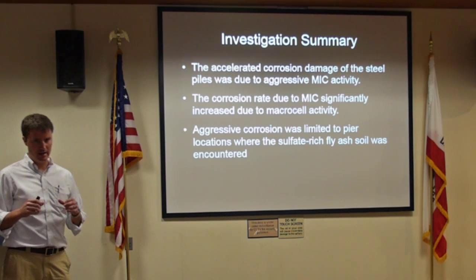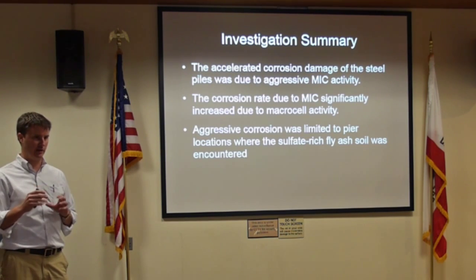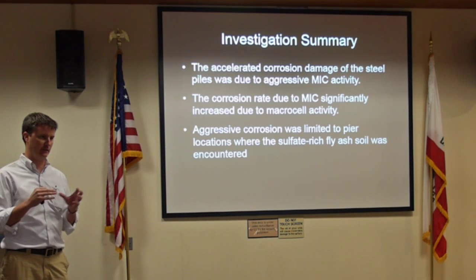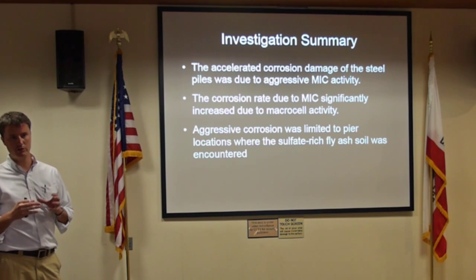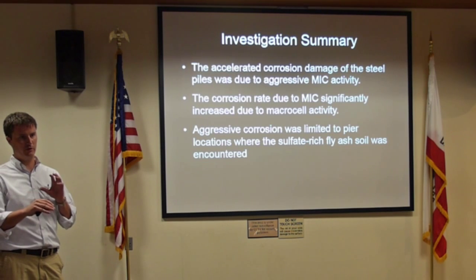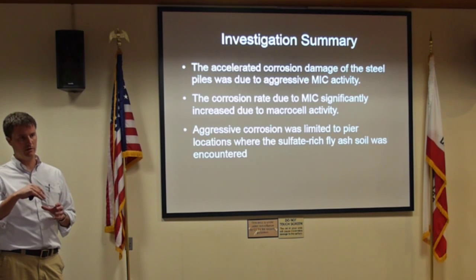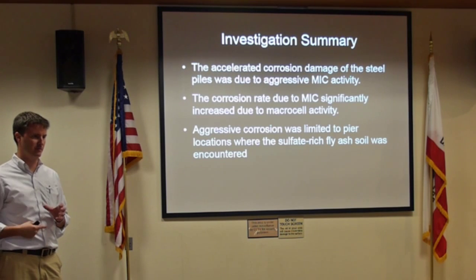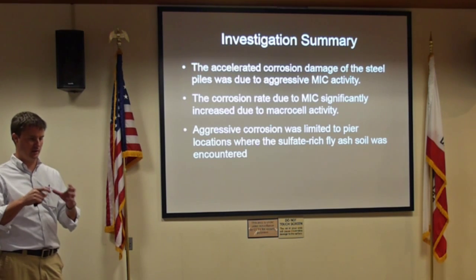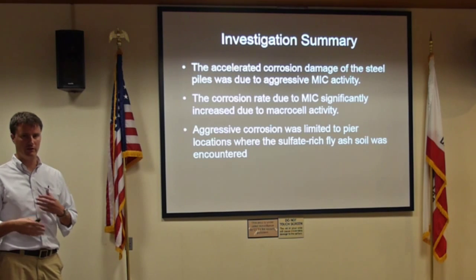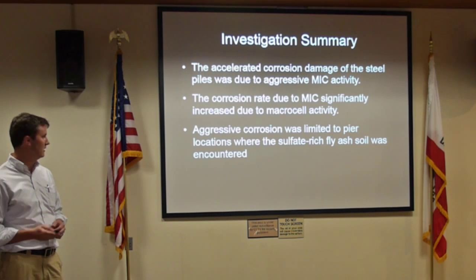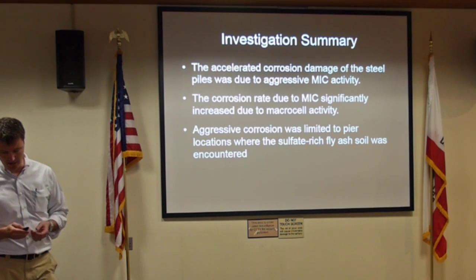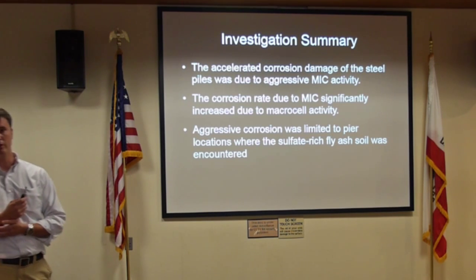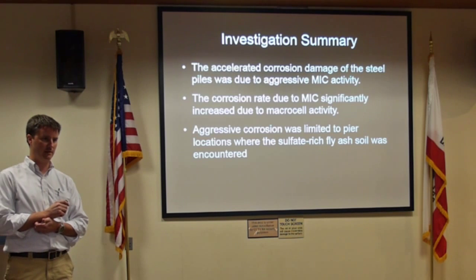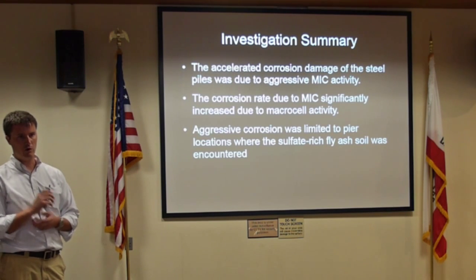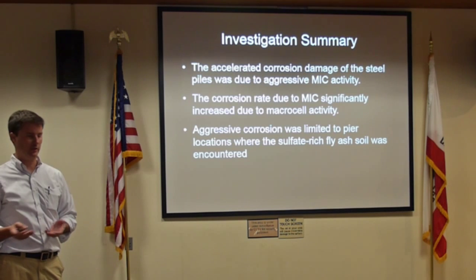And then in addition to that, we talk about these microcells and macrocells. That's on a micro level, happening very locally where the conditions are conducive. But then you have two different environments, if you will, and that ultimately drives what's called a macrocell, or a larger condition with differential conditions, a macrocell or galvanocell. We also found that of the 40 piers on this bridge, we opened up about 13 of them, and of those 13, only about 5 or so had very severe corrosion conditions.